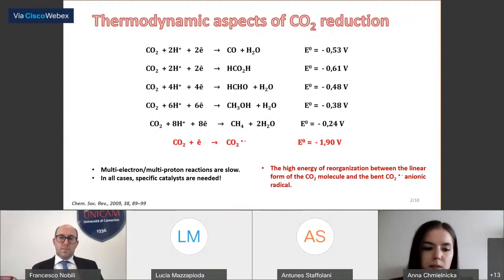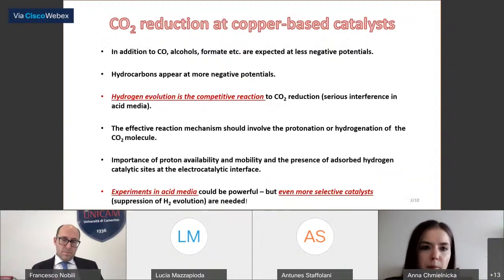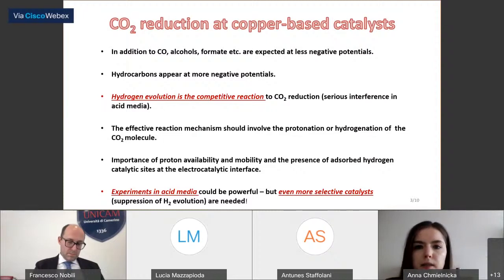It is possible to do this by using metals or metal oxides which adsorb carbon dioxide very strongly. Copper and copper compounds are the most promising from the point of view of catalytic ability, which does not mean it is a practical catalyst. So the important issue during carbon dioxide reduction at copper-based catalysts is that hydrocarbons appear at more negative potentials. In addition to carbon monoxide, alcohols and formate are expected at less negative potentials. Hydrogen evolution is the competitive reaction to CO2 reduction.